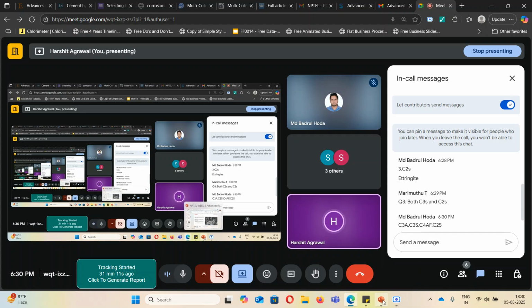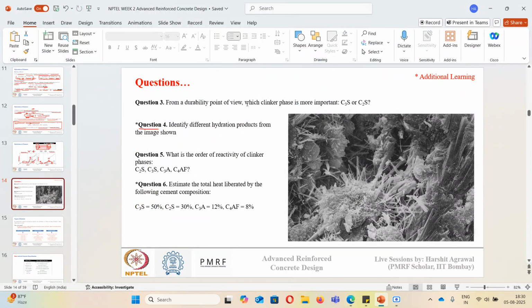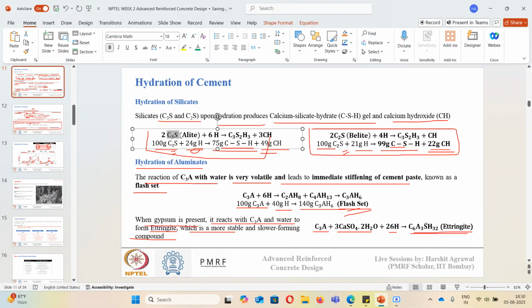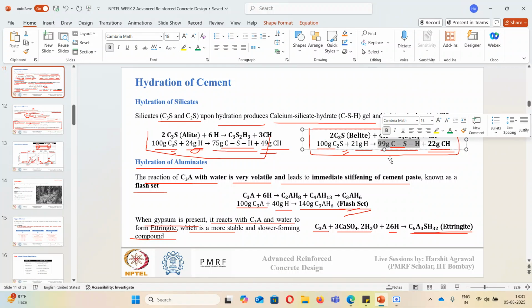Okay, let's see the solution now. From a durability point of view, which clinker phase is more important? The right answer is C2S. If you see these hydration reactions, C3S produces a lower amount of CSH and more amount of CH upon hydration, while C2S produces more amount of CSH and a lower amount of CH. This CSH is the main strength contributing phase in cement hydration, and the more its amount, the more durable my concrete will be.